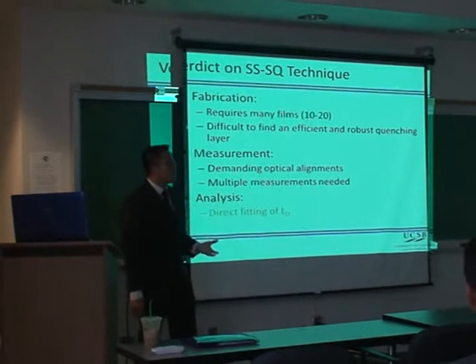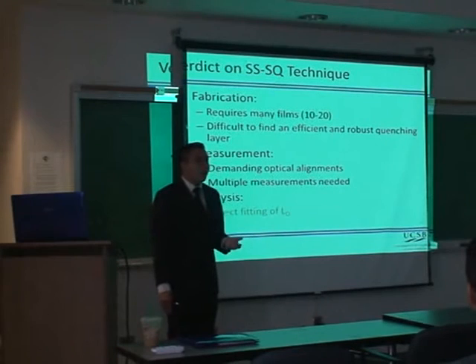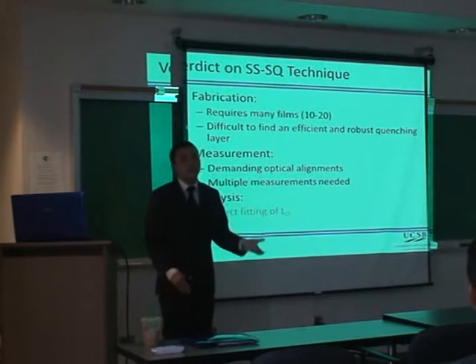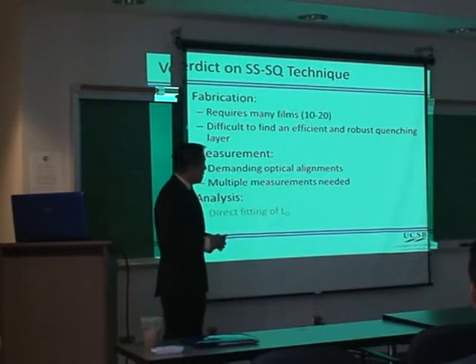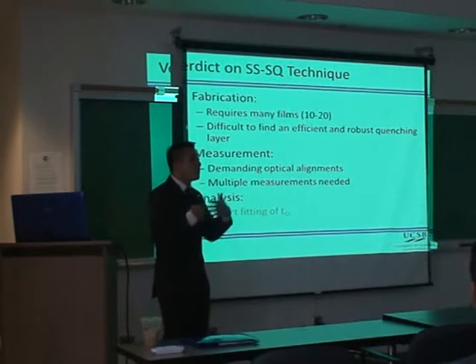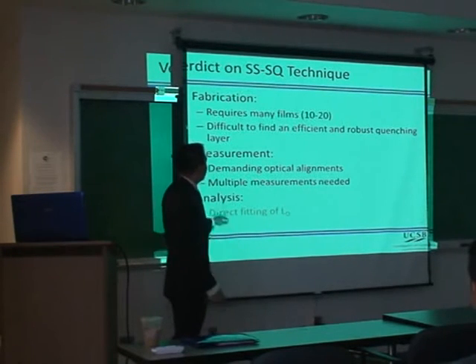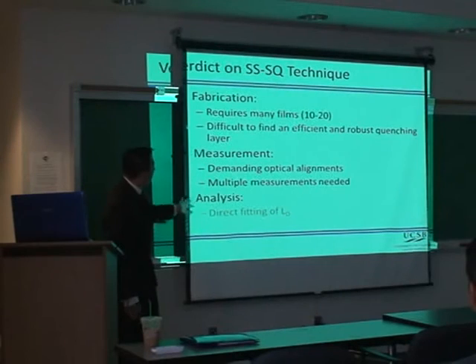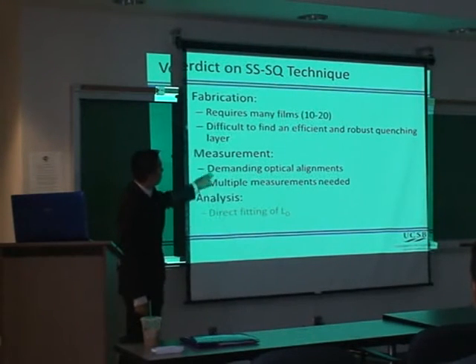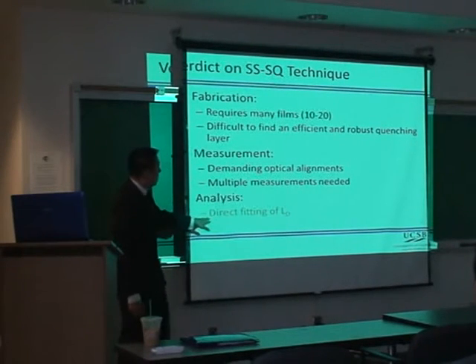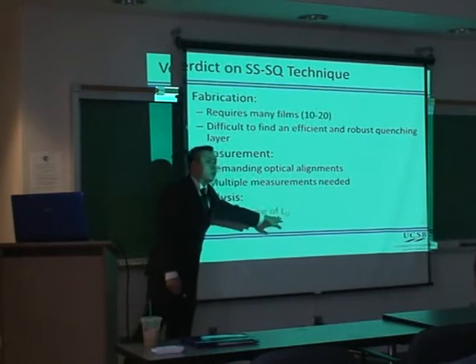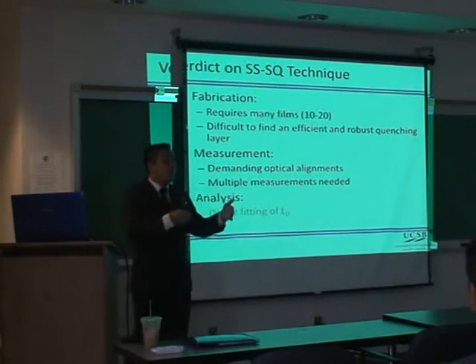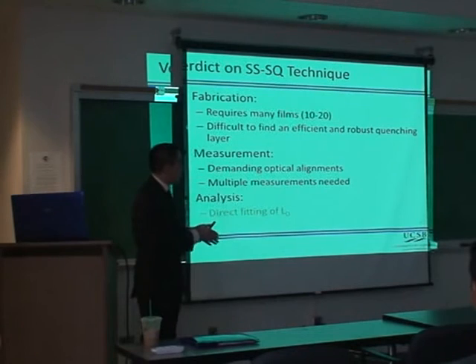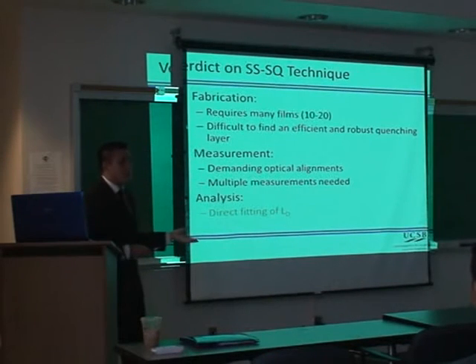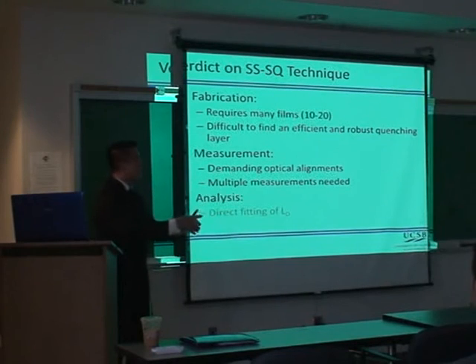In addition, I did mention that there's also a lot of other measurements that you have to do. You have to make sure that you know the exact thicknesses of these films, and you have to know the optical constants. You have to know the index of refraction and the extinction coefficient, and that requires additional modeling with spectroscopic ellipsometry. Finally, the one good thing is that it does fit for the exciton diffusion length directly. You are fitting to that number directly, so you're measuring that. Other techniques, which I'll discuss after, actually figure out a different value and then calculate the exciton diffusion length.